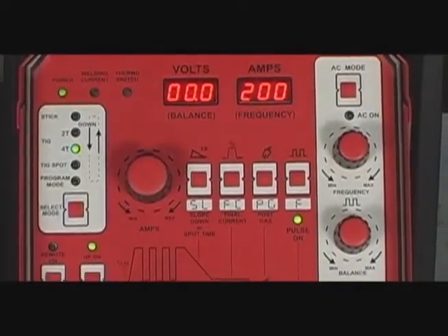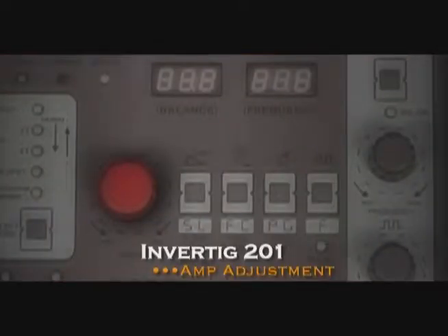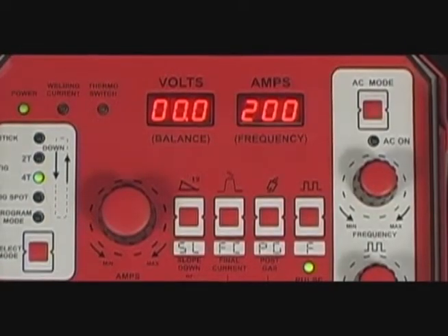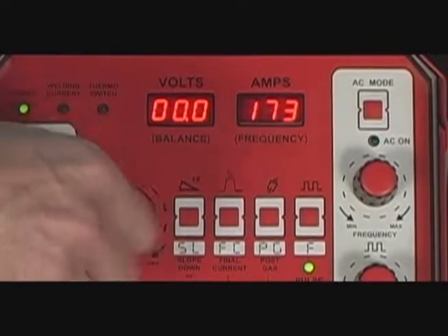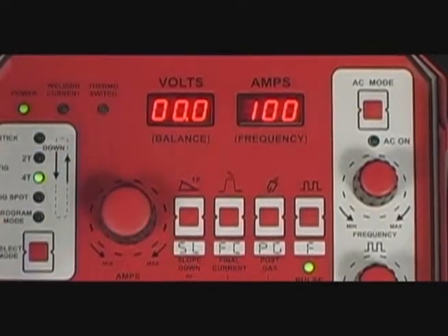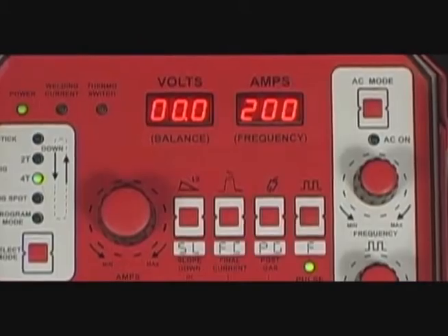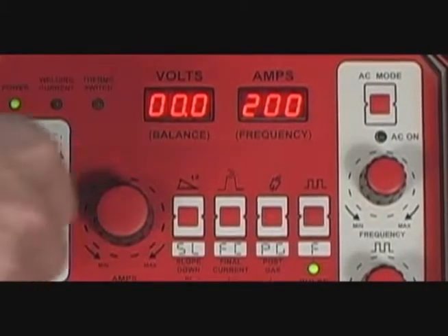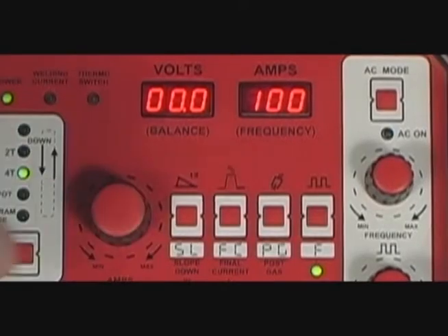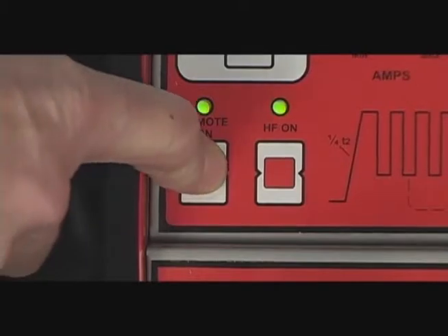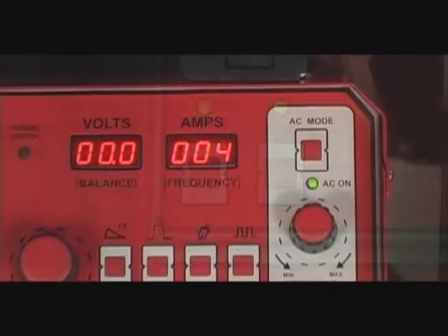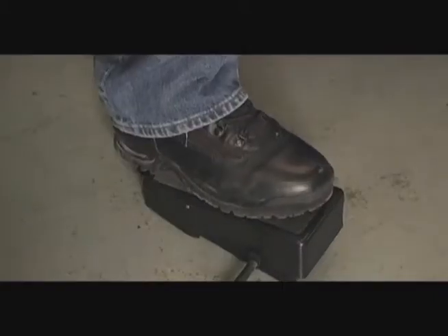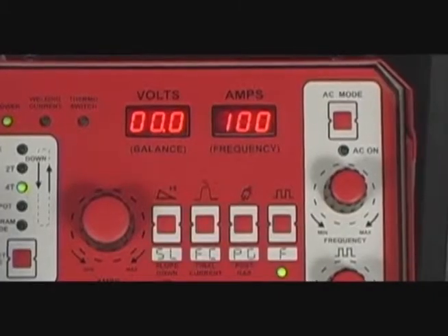When using a remote amperage control, the amperage adjustment knob is used to select the maximum amperage for your particular welding application. For example, when welding 50 thousandths 6061 alloy aluminum, I want to limit the output of the machine to 100 amps. I turn the remote off and set the amperage to 100 amps. This is about 20% more power than I will need to weld the aluminum. I turn the remote switch back on and the digital display shows the starting amperage of 4 amps. If I were to depress the foot pedal completely, the maximum amperage would now be 100 amps.